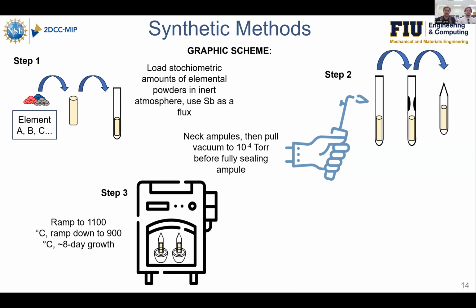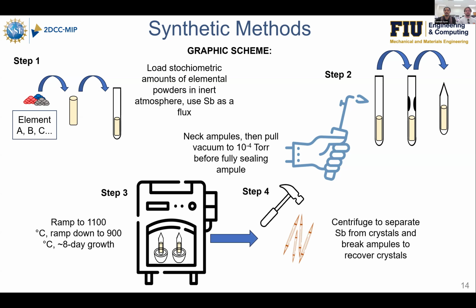The growth profiles for these are a ramp up to 1100 degrees C, a controlled ramp down to 900 degrees C, and overall this entire growth process is about 8 days, give or take, maybe an extra day depending on if the growth was set up before a weekend or anything like that. Finally, these ampules are centrifuged to separate the antimony flux from the crystals, which allows us to break the ampules to recover the actual crystals.